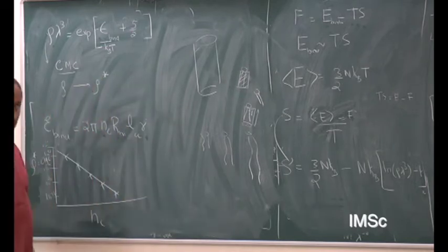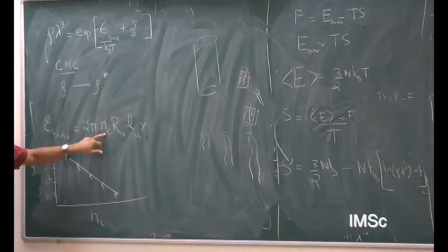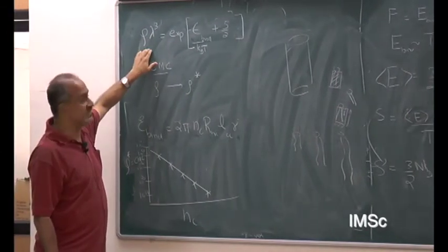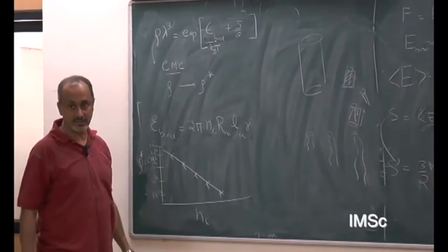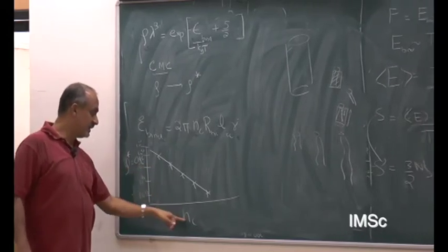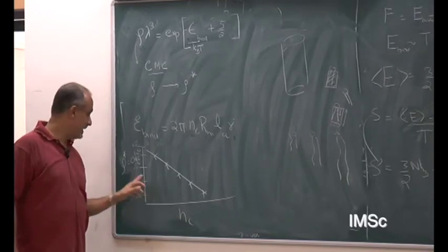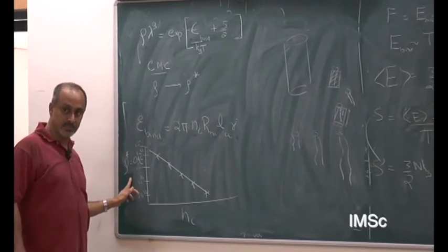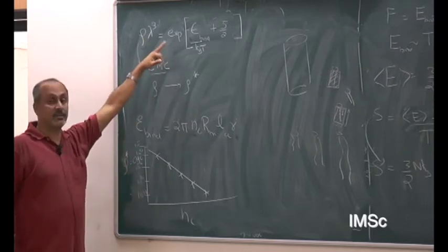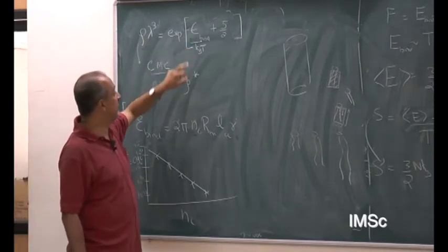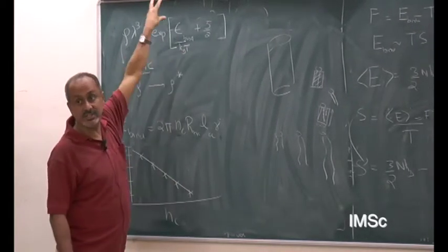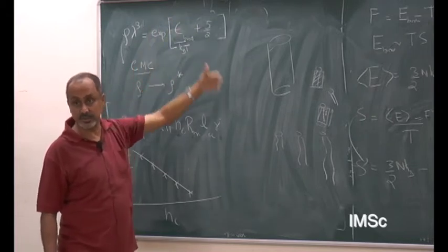Once I put that in, because essentially that enters in this factor here, and this is the relation that tells me that this should be my density at which I now begin to aggregate these molecules together, then this predicts a relationship between the number of carbon atoms in the tail and the critical micellar concentration. And this is a very strong dependence because this is an exponential dependence on the number. This E_binding depends upon N_C. So this is exponential of that, which is usually a much stronger dependence.